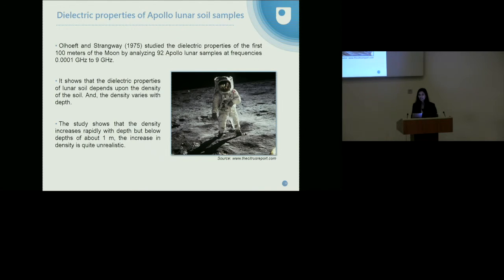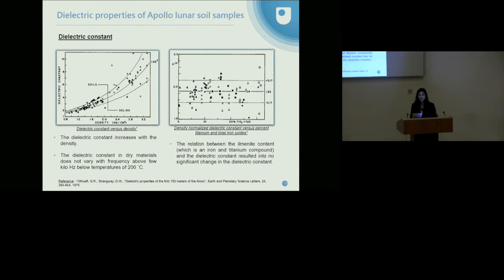soil samples collected from Apollo missions to analyze up to the first 100 meters of the moon by testing at frequencies from 0.001 gigahertz to 1 gigahertz, and some samples were even tested at 9 gigahertz. They tried to establish the relationship of dielectric properties with the density. They also found out that the density varies with the depth as well. The density did increase with the depth, but below the depths of about 1 meter, they commented that the results were quite unrealistic. When they looked at the dielectric constant, they found that the dielectric constant increases with increase in